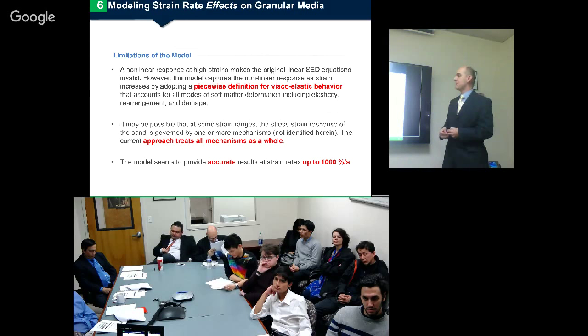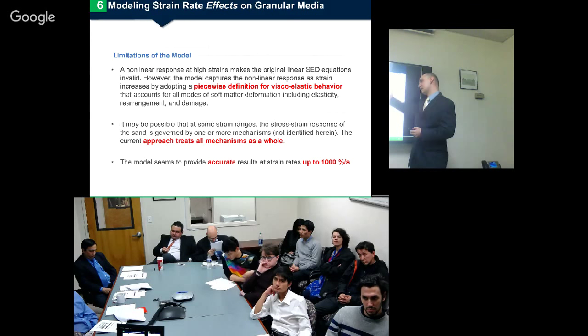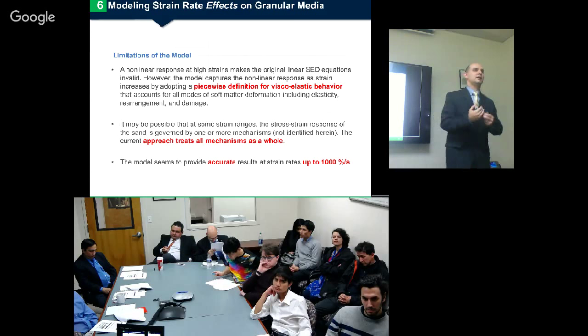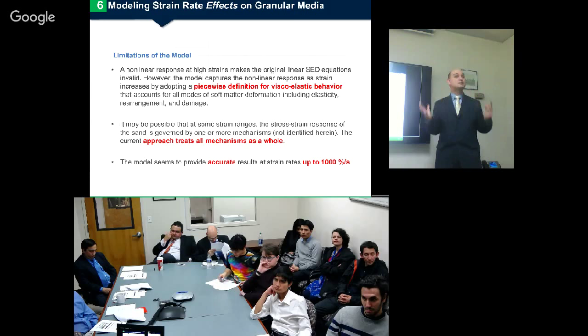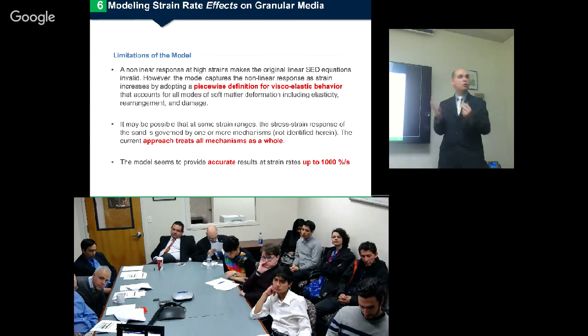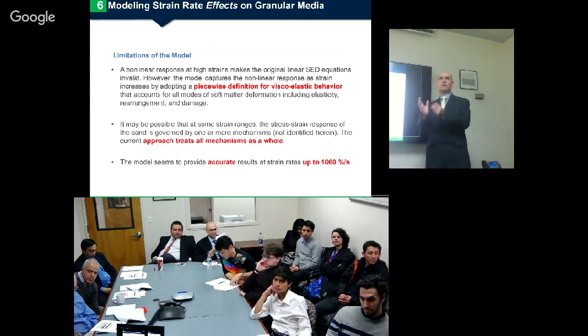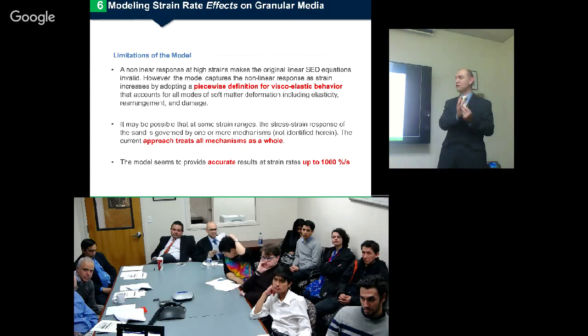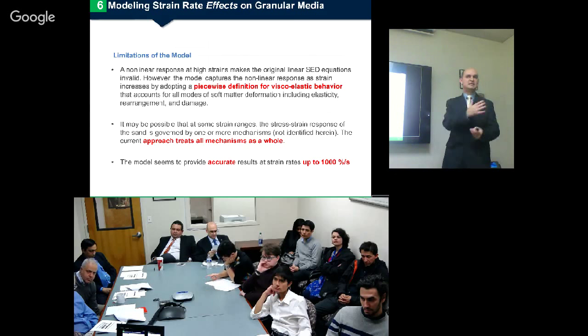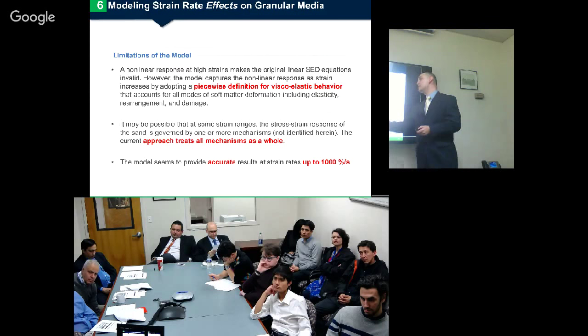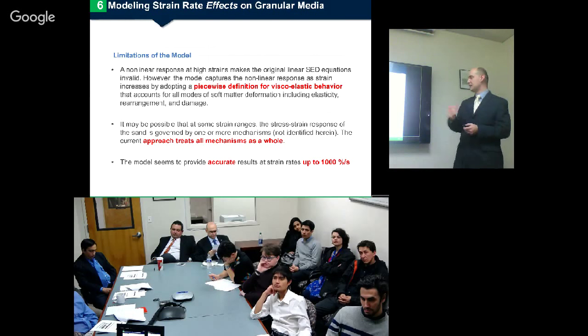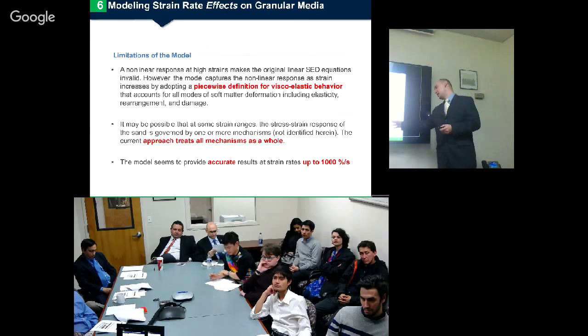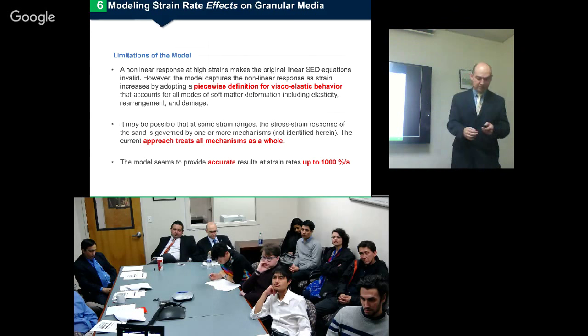So again, I think this is similar to this. The approach provides the response and shows the behavior as a whole, without distinction of what part of the model is governed by elasticity or by rearrangement of the particles. And the model seems to provide accurate results at a strain rate up to maybe a little bit lower than 1000% per second.